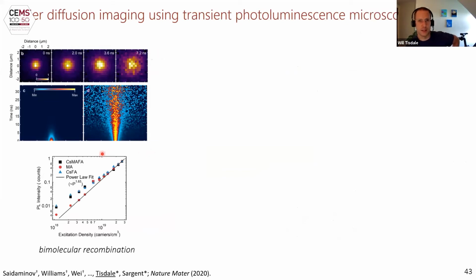The analysis of this data is not nearly as straightforward as it is in the case of exciton transport. And this is all because of the nonlinear dependence of the photoluminescence on the excitation density. So in this free charge carrier material, bimolecular recombination dominates. That's the recombination of free electrons and free holes. And because your local photoluminescence intensity is the product of your electron density and your hole density, your photoluminescence scales quadratically with your excitation density.